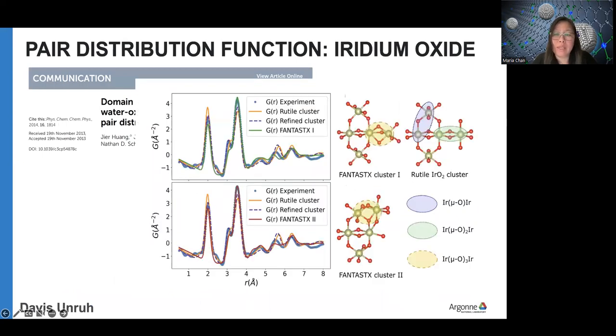In other cases, on the X-ray pair distribution function, I remember this example because I talked to the postdoc. We weren't on the same project, but he was tearing his hair out fitting this PDF. You can start with a rutile structure of iridium dioxide and tweak the positions of the atoms. You can get a good fit, but then there's a lot of, again, back and forth manual fitting, and also starting with a very biased starting point, which is rutile. Instead, in FANTASTX, we threw atoms in a box. We had sort of a pseudo-amorphous type structure, which is still periodic, but a biggish cell. We let FANTASTX run with a multi-objective approach, which balances both the fit to experiment as well as the energy of the structure. And it found the structure, again, in maybe a week or two on the cluster.